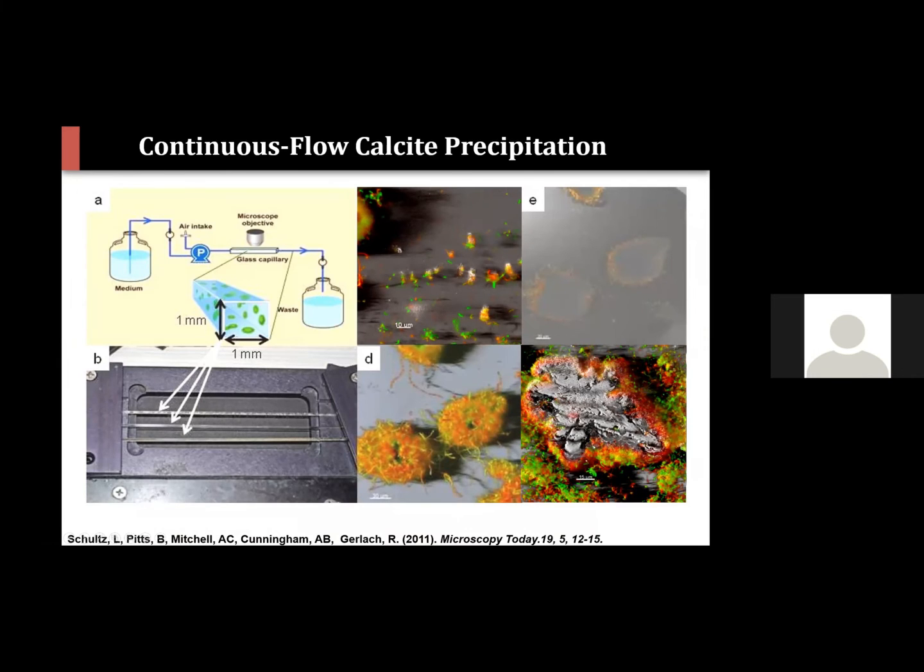real time to look at the association of cells here in green and the carbonate precipitates in white here. Obviously we can see that there are cells on the reactor surface and we see the crystals grow. But ultimately, we also see more cells associated with the precipitated crystals than we do with the wider reactor surfaces. So it seems that there's preferential association with calcium carbonate, where we get growth and encasement repeating, where ultimately the growth of cells seems to exceed the encasement.